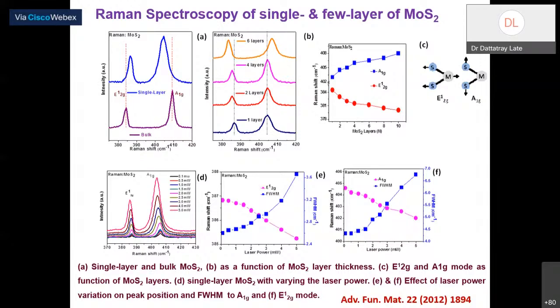Depending upon thickness, for example, you can see 10 layers of MoS2, 8 layers, 6, 5, 4, 3, 2. Another important parameter to note is the peak frequency difference between these two peaks. For bulk MoS2, the peak frequency difference is almost 26 inverse centimeters. The moment you make a monolayer of MoS2, it changes from 26 to 18 inverse centimeters. This is an important characteristic to distinguish whether my sample is 1 layer, 2, 3 or 10. For 10 layers the difference is 26 and for 1 layer it is 18 inverse centimeters.